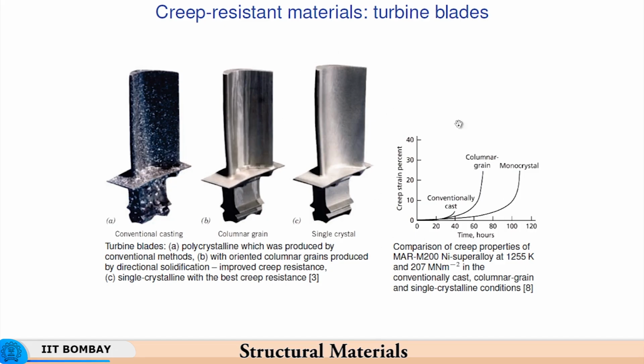So, if you look at the creep resistance, the creep strain percent is shown here. The conventionally cast material within say 30-40 hours itself will have significantly higher creep strain, whereas for the same thing to develop with columnar grains, you will need something like 60 to 70 hours, and for the single crystal, even beyond 100 hours it will last. So, the creep strain percent increases far too slowly with large grain sizes, or even a single crystal, as compared to a conventional cast condition.